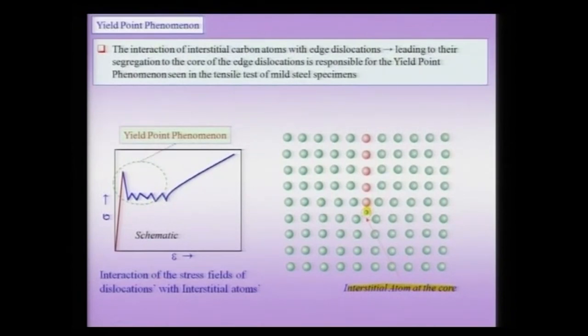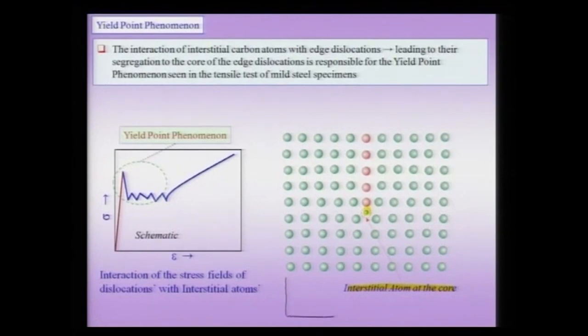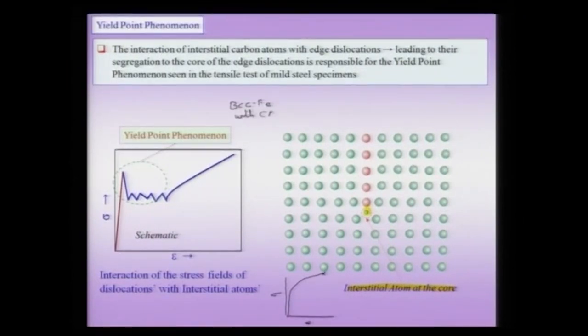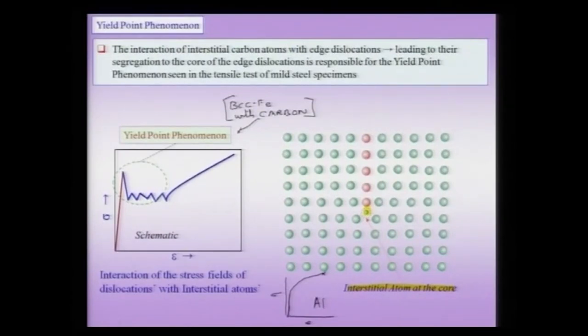What is the signature of this on the stress-strain diagram? For a material like aluminum, the stress-strain curve goes up straight without a distinctive yield point. But for BCC iron with carbon, a clear signature is seen in a phenomenon known as the yield point phenomenon. For aluminum, the material shows an elastic region and then the curve bends gradually as dislocations move and continue to cause plasticity.